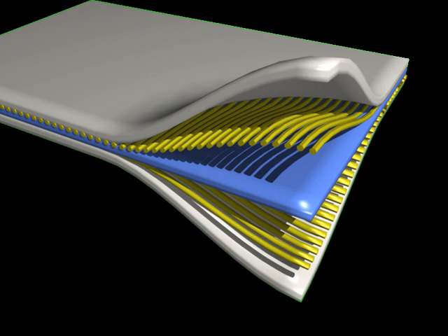Though composite stiffness is maximized when fibers are aligned with the loading direction, so is the possibility of fiber tensile fracture, assuming the tensile strength exceeds that of the matrix. When a fiber has some angle of misorientation theta, several fracture modes are possible. For small values of theta, the stress required to initiate fracture is increased by a factor of cos^-2 theta due to the increased cross-sectional area A/cos theta of the fiber and reduced force F cos theta experienced by the fiber, leading to a composite tensile strength of sigma_parallel/cos^2 theta, where sigma_parallel is the tensile strength of the composite with fibers aligned parallel with the applied force.